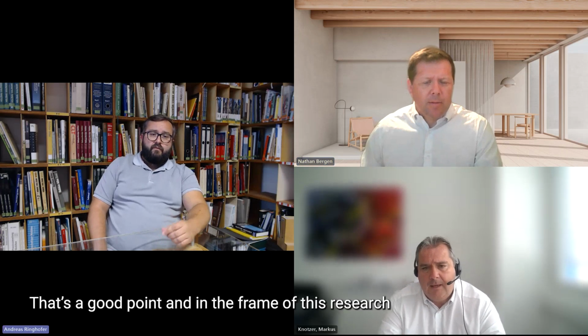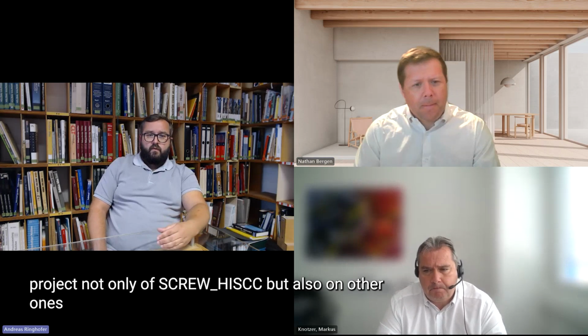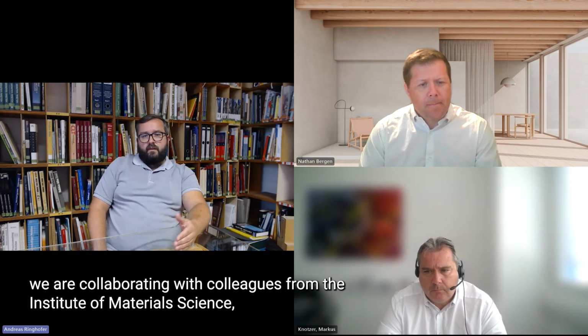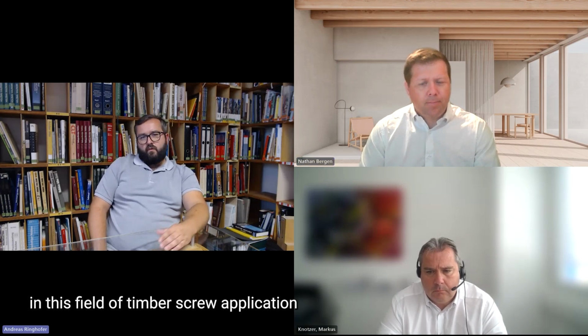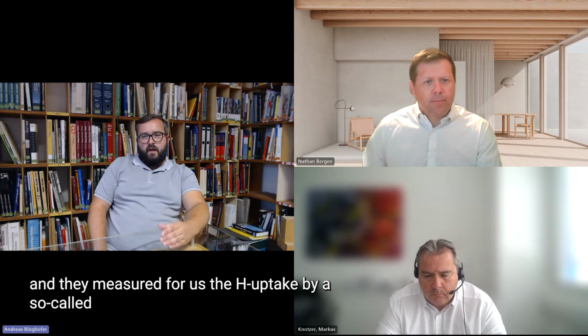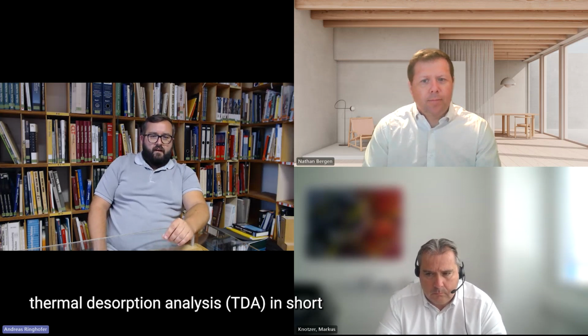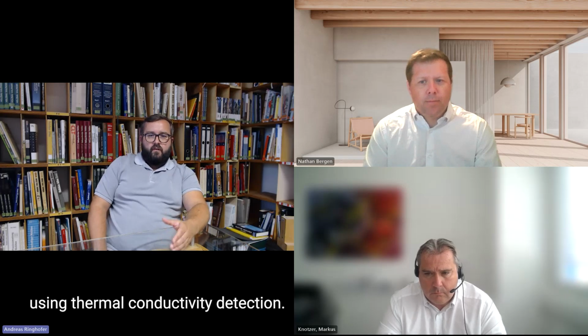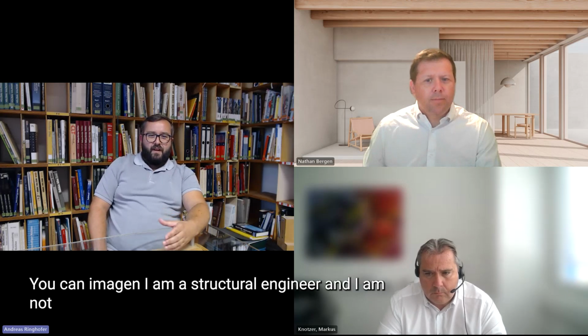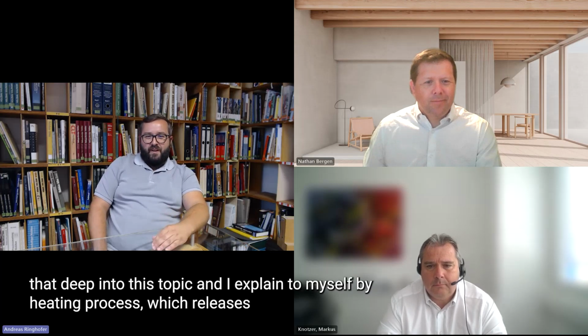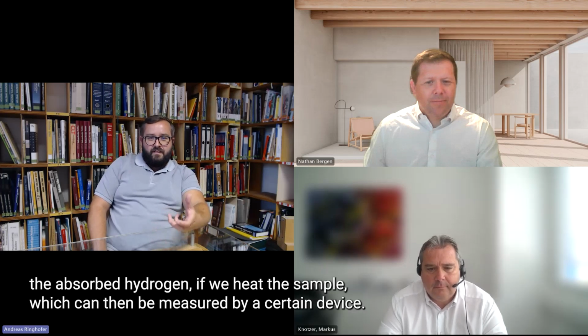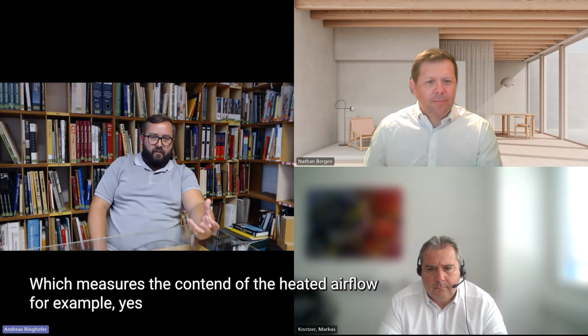That's a good point. In the frame of these research projects, not only of the SCREW HISCC, but also some other ones, we are collaborating with colleagues from the Institute of Materials Science, Joining and Forming of Graz University of Technology, because they are the experts in this field of timber screw application. They measured for us the hydrogen uptake by a so-called thermal desorption analysis, TDA in short, using a thermal conductivity detection. You can imagine, I'm a structural engineer and I'm not that deep into this topic, and I explain it to myself as a heating process, which releases the absorbed hydrogen if we heat the sample, and which can then be measured by a certain device, which measures the content of the heated air, for example.